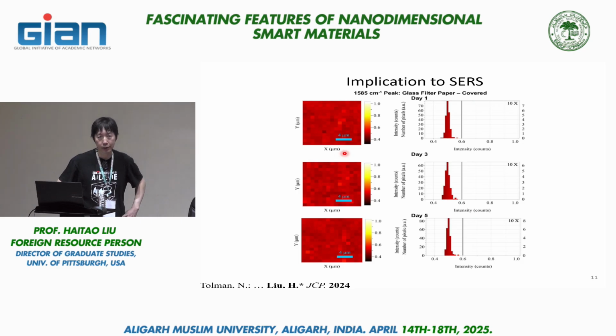Could be amorphous carbon cluster, could be aromatic carbon cluster, could be aerosol, could be a lot of things, but it does not seem to be a molecular species diffusing in air. Again, we do not know whether this is specific to the metallic substrate case, or is it broadly applicable to all the cases we have studied. Now remember, in the case of graphite, we have done ellipsometry measurement where we see this progressive growth of thin film, and in that case, it seems to indicate it's the molecular species that is adsorbed on the surface. But this one seems to be different.